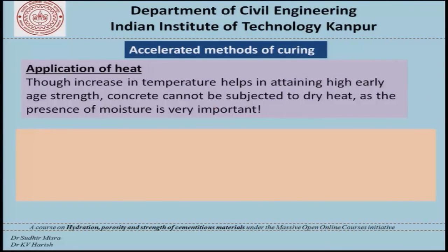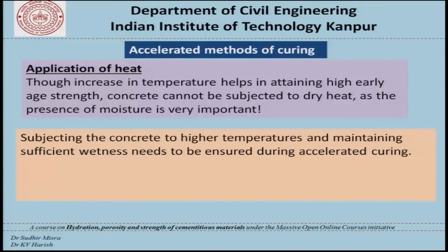Moving further, there are other methods such as application of heat. We must remember that though an increase in temperature helps in attaining high early strength, concrete cannot be subjected to dry heat, as the presence of moisture is very important to ensure the right kind of hydration and strength development. Subjecting the concrete to higher temperatures and maintaining sufficient wetness needs to be ensured during any accelerated curing.